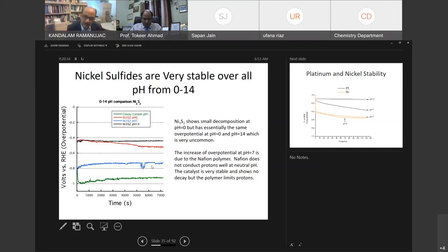In fact, this is the case whenever we use Nafion, because the protonic conductivity of the Nafion membrane is not very good at pH 7, and that is what is hampering the activity of the materials. But at pH 0 and 14, we have very good activity. One of the interesting aspects here is when you look at pH 0 or 14, the onset potential is exactly the same initially. This is very uncommon. So we're also pursuing this. Why is this potential independent of the pH?